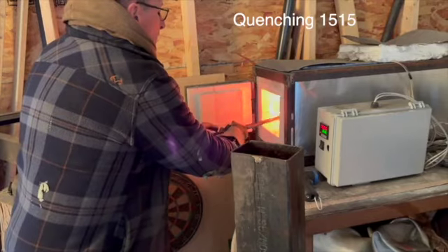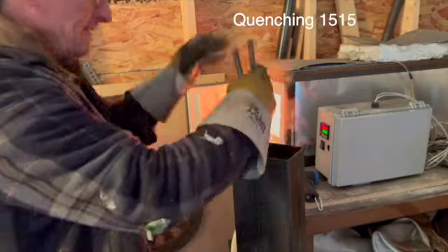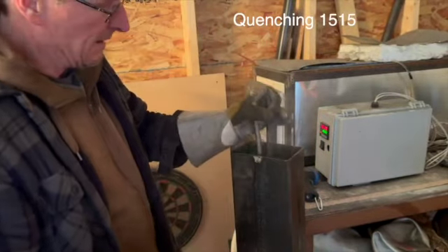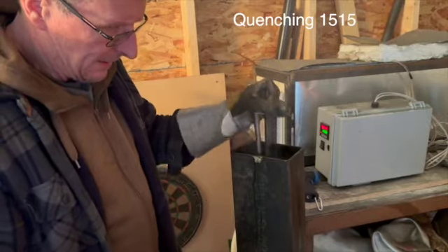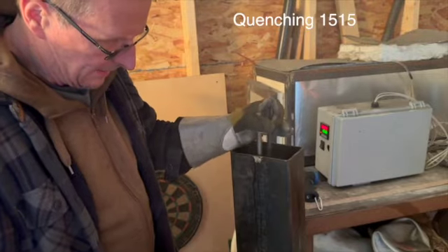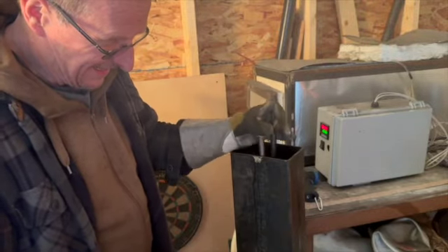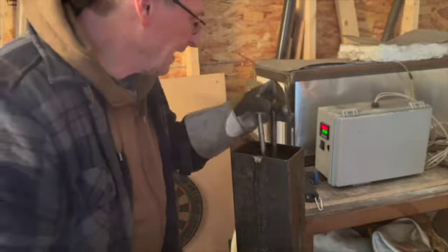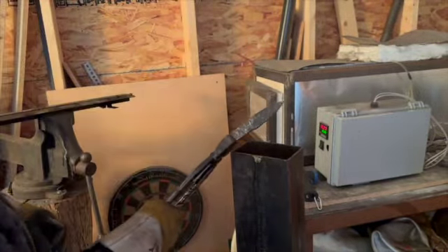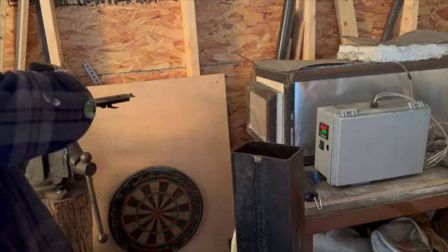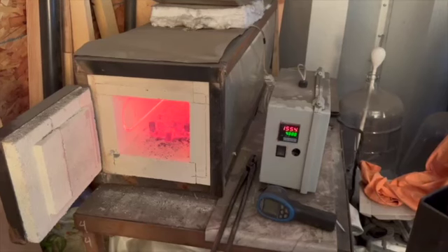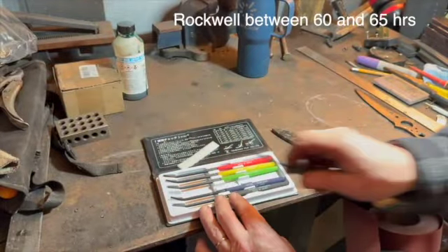For quenching, I add about 15 degrees. That way, when it cools off between transferring from the kiln to the quench oil, it should be at my target temperature. The oil is preheated to approximately 400 degrees, and I do that simply by quenching a block of mild steel that I've got kicking around.